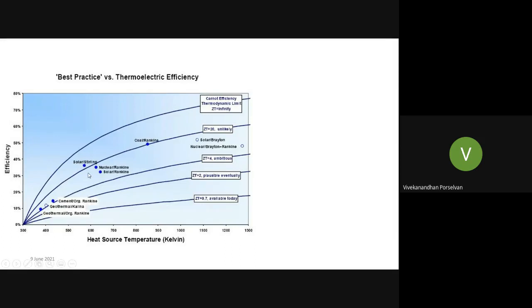If you are taking a solar energy based technique or nuclear, it lies at less than 40%. And geothermal or some other source comes close to 10% operating efficiency, whereas the thermoelectric efficiency we have is very low. ZT is less than 1, whose equivalent value in terms of percentage is 10%. So to achieve close to 50%, we have to increase the ZT value to more than 5, so that we can replace these conventional practices.